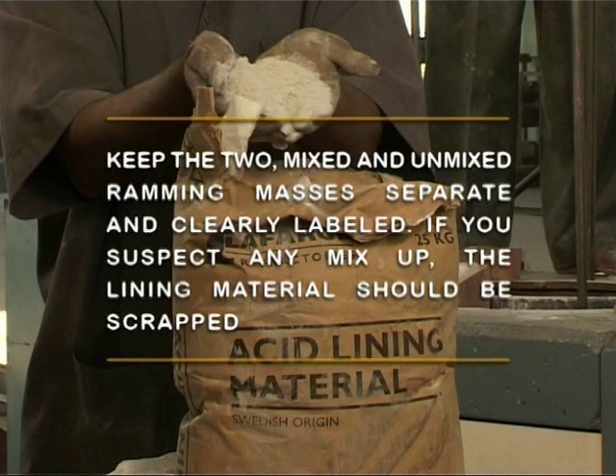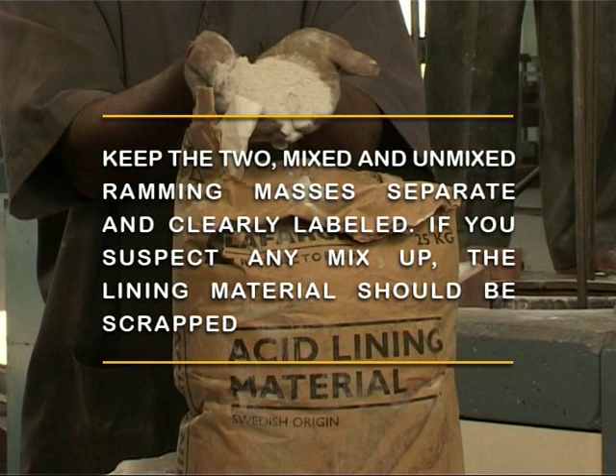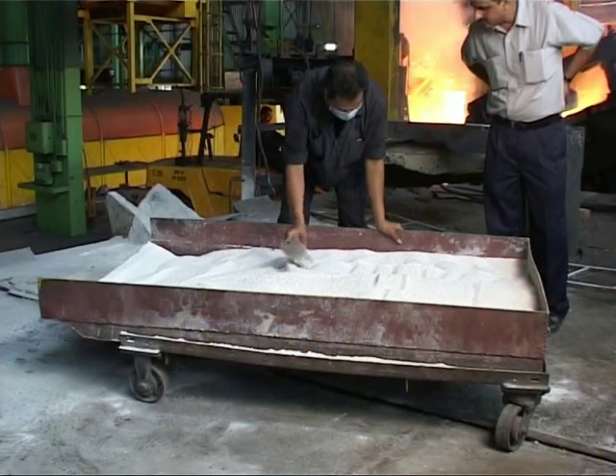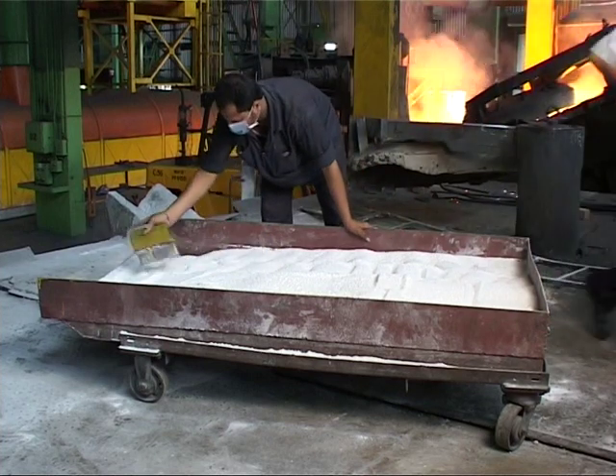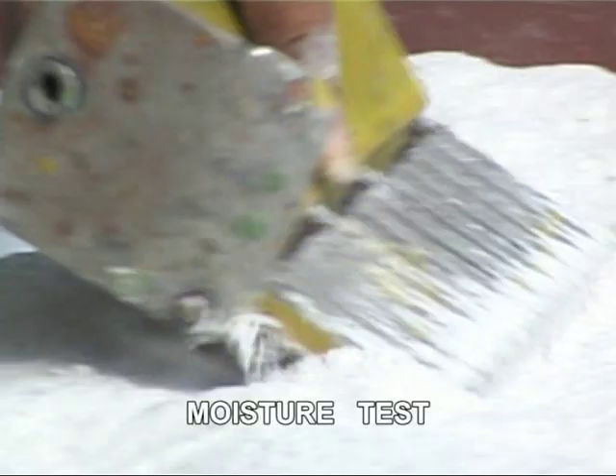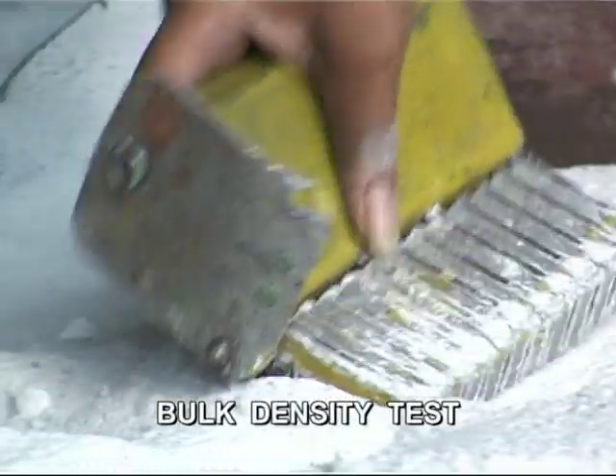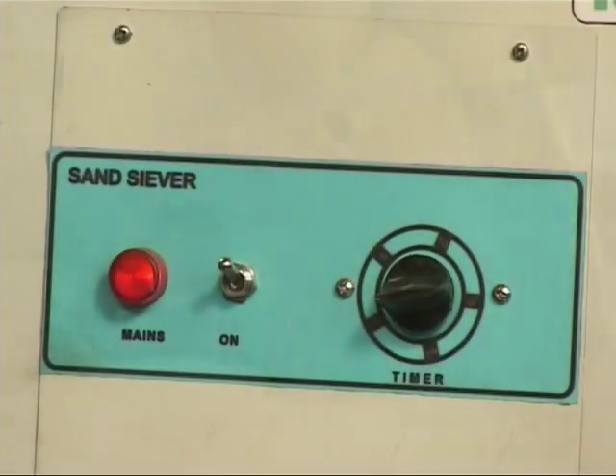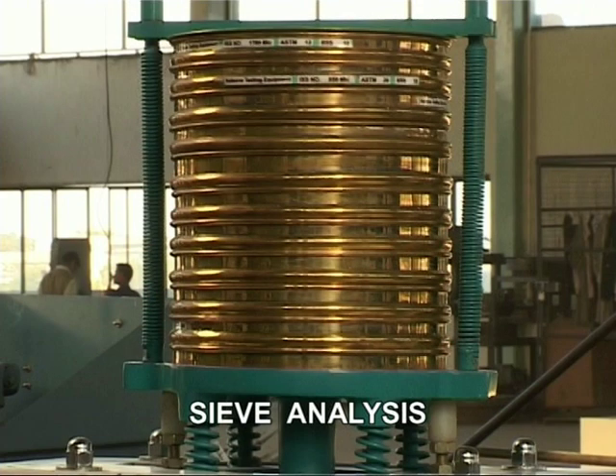Keep the two, mixed and unmixed ramming masses, separate and clearly labeled. If you suspect any mix-up, the lining material should be scrapped. If, however, you prefer to mix your own ramming mass, stick to this only. Keep only one type of ramming mass to avoid mix-up. All types of ramming mass should be tested before use for moisture, bulk density, iron particles, and sieve analysis.